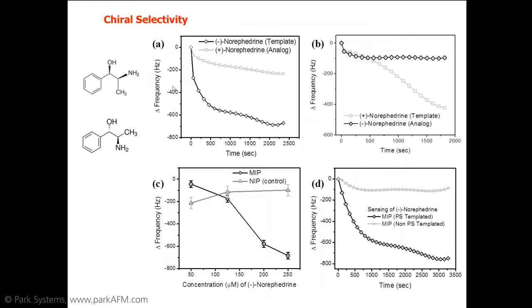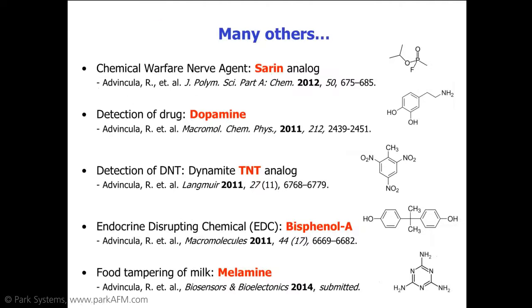Here it shows that we have very good chiral selectivity. If we template it originally with one enantiomer, we get good response. On the other hand, if we template it with the opposite enantiomer, we get a good response of the opposite enantiomer as well. Here, MIP was demonstrated between the PS templated and non-PS templated sample, and here between the MIP and the NIP. So MIP here shows that you have the higher frequency response.